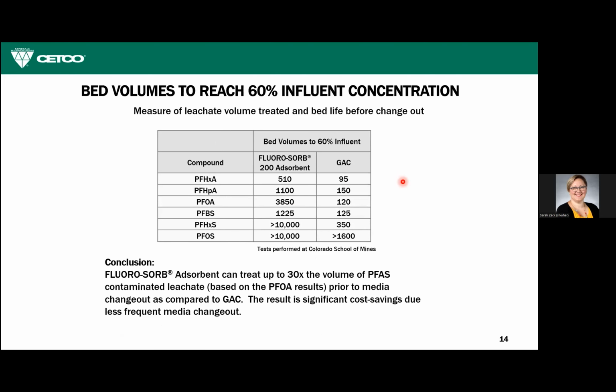So the conclusion is that Fluorosorb was able to treat many more bed volumes for all different PFAS compounds than the comparison to GAC, and that was judged by treatment to 60% of the influent concentration. And we have several full-scale landfill leachate systems that are going in specifically because Fluorosorb is not affected by the background or the other water quality constituents.